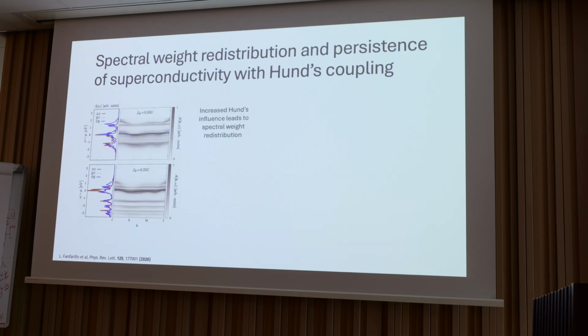Next, this paper goes a step beyond just the quasi-particle spectral weight by including the dynamical effects, DMFT. And what they find is that the increased Hund's influence leads to spectral weight redistribution in an energy window J_H around the Fermi level. So for low Hund's coupling, they have some characteristic DXY around the Fermi level and DXZ, DYZ, whereas when you increase this Hund's coupling, the DXY is suppressed and actually the XZ/YZ is increased.